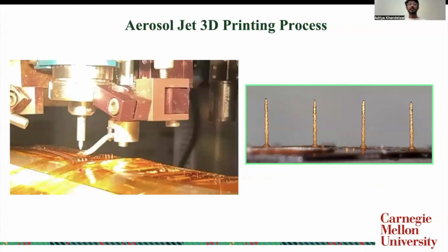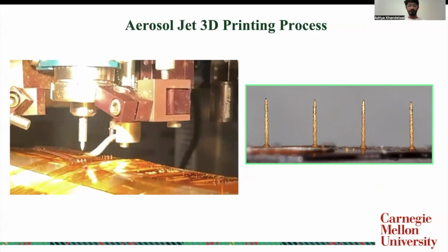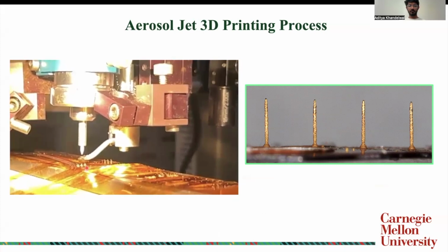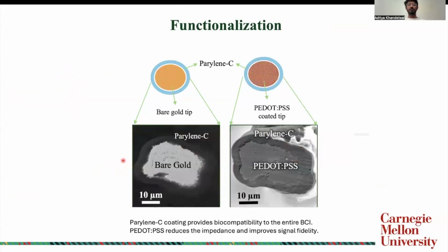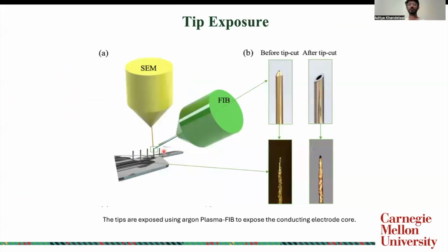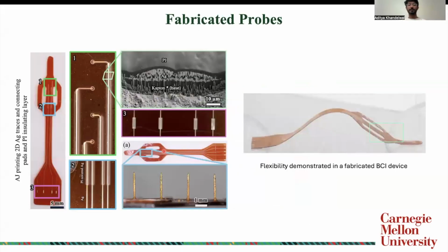In this video, you can see the deposition of printing. After printing of the probes, we functionalize them by coating with parylene, which offers biocompatibility to the probe, and to lower the impedance and improve signal fidelity, we electrodeposit PEDOT:PSS. Finally, we expose the electrode tips using argon plasma etching. This is done to expose the electrically conductive gold core, which will be able to harness the signals.